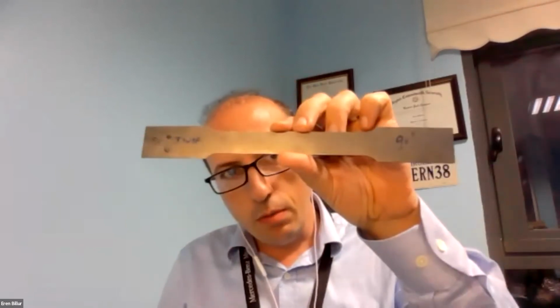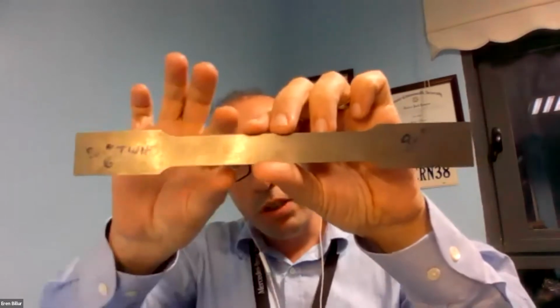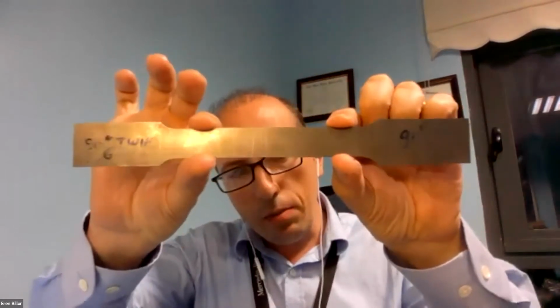Hi there. Shall I continue? Okay, so I had a few comments about elongation and N value. First of all, there are a number of different elongations. The simplest difference is uniform elongation and total elongation. For most steels, N value and uniform elongation are hand in hand. But the problem is we typically see total elongation in the mill cert, and there is a difference in total elongation. In Europe, this is the tensile specimen that we use. This is 20 millimeter wide, and the gauge length is 80 millimeters.